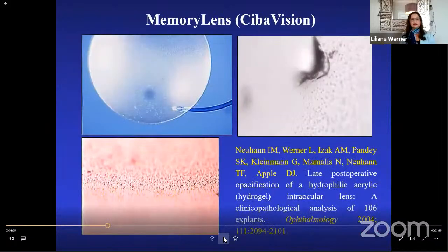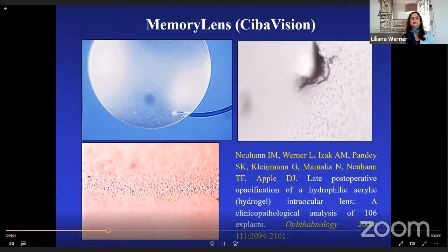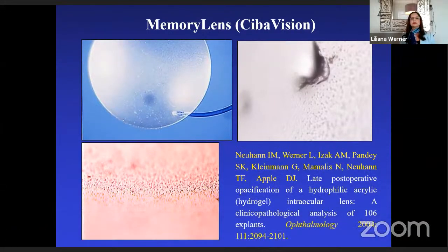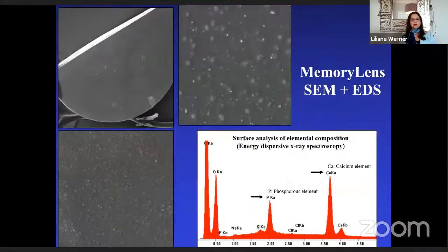Later, we received many lenses explanted because of postoperative opacification, which were of the memory lens design. With this lens, a thin granularity was usually covering the optical surface of the lens. Once again, the surface analysis confirmed that the composition of the granularity was calcium and phosphate.